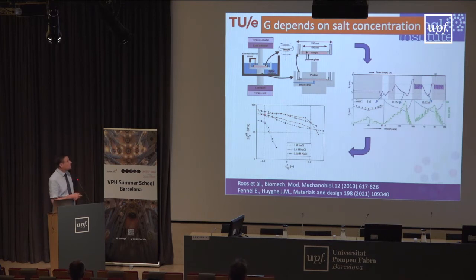And we did actually experiments. Here, this is a gel enclosed from all sides within a torsional testing bench and within a ring so that it cannot swell or shrink, but we can change the salt concentration in the bath. And then you find changing stiffness depending on the salt concentration. These are three different salt concentrations, 0.03 molar, 0.1 molar, 1 molar. As you change the salt concentration, even at constant strain, you still get a different stiffness.